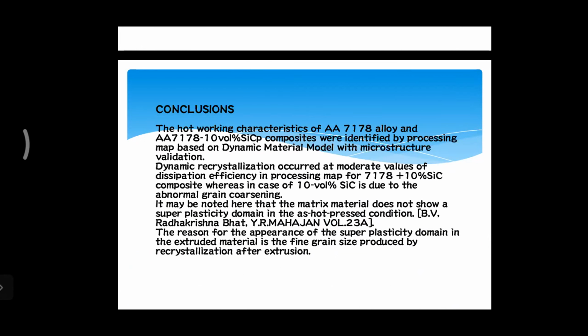And dynamic recrystallization occurred at moderate values of dissipation efficiency in the processing map in the case of the composite, whereas in the case of 10-vol% SiC, it is due to abnormal grain coarsening. So this is one of the reasons. It may be noted that here the matrix material does not show a superplasticity domain, as it was represented in the Y.R. Mahajan paper. So the reason for the appearance of the superplasticity domain in the extruded material is the fine grain size produced by the recrystallization after extrusion.